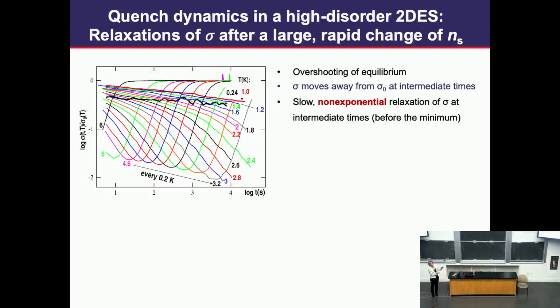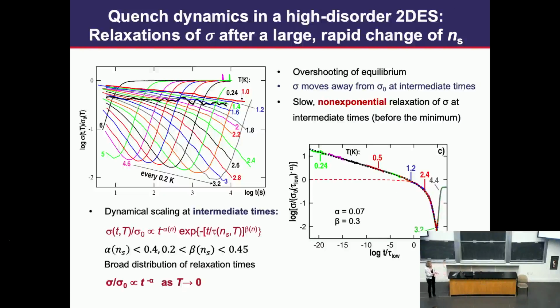As you wait, the conductivity goes away from equilibrium, then it goes through a minimum, and at later time it approaches equilibrium. At lower temperatures, this process is slower and slower, and it turns out you can collapse all of these curves before the minimum onto the same function, which is a product of a power law and a stretched exponential. In the zero temperature limit, this reduces to a pure power law.